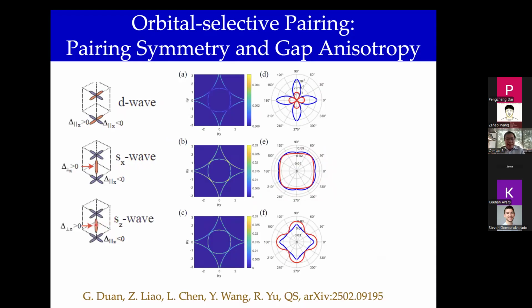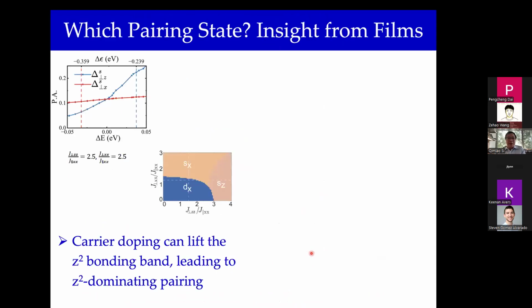However, for the extended s-wave where the dominant pairing amplitude is associated with 3d z-squared orbitals, we found that across the Fermi surface there's quite a significant variation of the contributions from the different orbitals. And that leads to, at least compared to the other two, the d-wave and the other regime of extended s-wave pairing, a significant variation of the gap. And so that's important in comparing. And one more feature, because we want to think about the films. I already mentioned that the films of the bilayer nickelate are built on a substrate that compresses the nickelate within the xy plane.